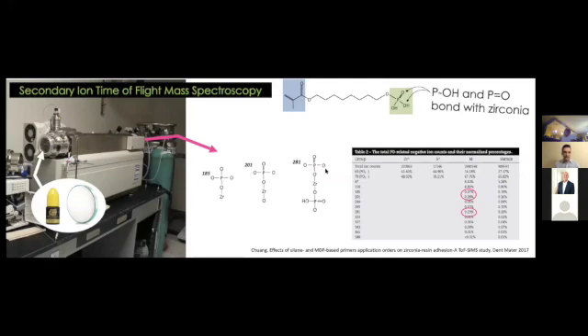How mass spec works is that you take some of the zirconia and some of the MDP, and essentially you combine them together in this end of the tube, and then I think you ionize it, or somehow you blast it and kind of blow it up. And then you shoot it down this tunnel, and at the end of the tunnel, it measures the molecular weights of all the different fragments that came from when you blew up this MDP bonded to zirconia. And let's say that MDP and zirconia don't bond. What you would see at this end of the tunnel was blasted up fragments of MDP and blasted up fragments of zirconia, but you'd never have any fragments that corresponded to pieces of zirconia bonded to pieces of MDP. But they did. They found fragments of pieces of zirconia bonded to pieces of MDP. And so that was a way for them to say, okay, these things must be bonding strong enough so that when they get blasted and sent down the tube, they're still attached to each other.